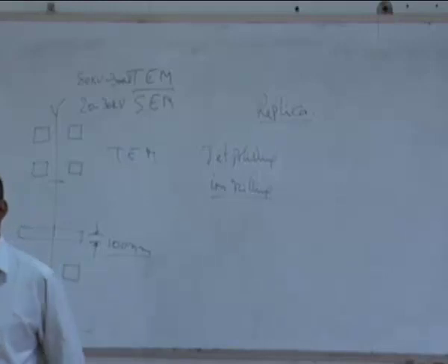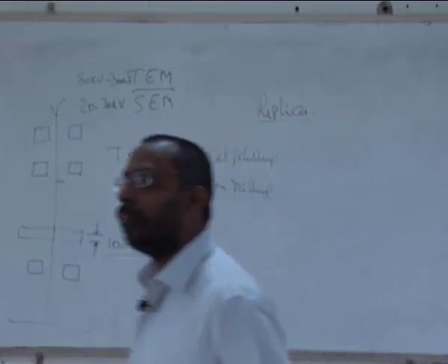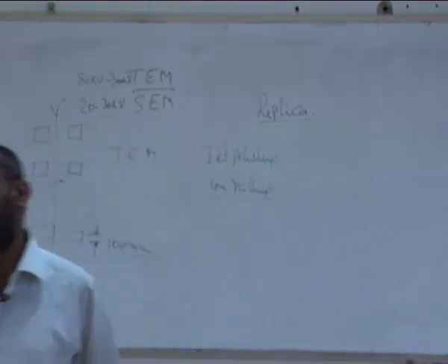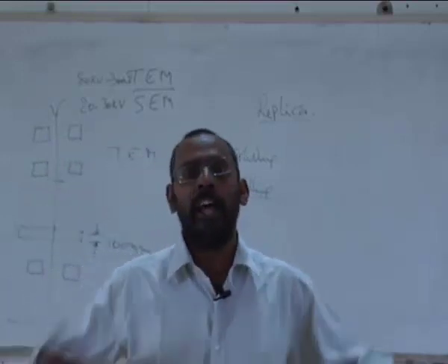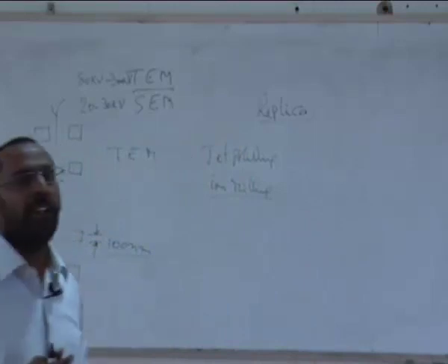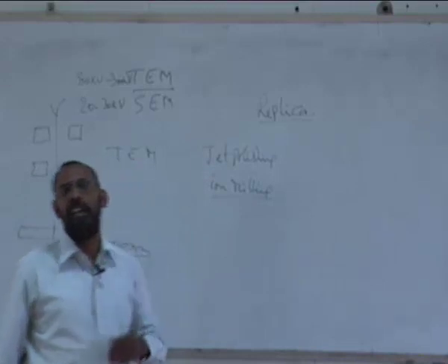Though we mentioned yesterday that ion milling is used for non-conducting samples, you can also use ion milling for even conducting samples whenever you see that the sample is very reactive. For example, if I have a titanium alloy, if I put this titanium alloy sample into an electrolyte and allow it to dissolve using a jet polishing technique, you see that in the process it may get oxidized. So you may have a thin oxide layer forming on the surface, which disturbs the microstructure that you are seeing. As a result, you need to possibly go to a technique where such oxide layers cannot be formed.